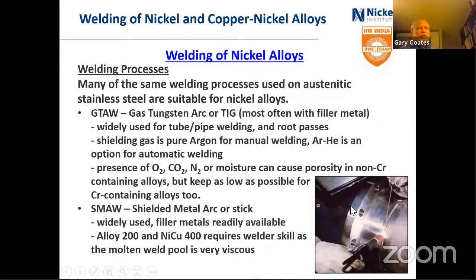When we come to welding processes, many of the same processes used on austenitic stainless steel are suitable for nickel alloys. Gas tungsten arc welding or TIG welding is commonly used, especially for root passes. The shielding gas is pure argon, usually for manual welding. The backing gas would also normally be pure argon. Argon helium is used for automatic welding, where you can get higher speeds and in a consistent manner.